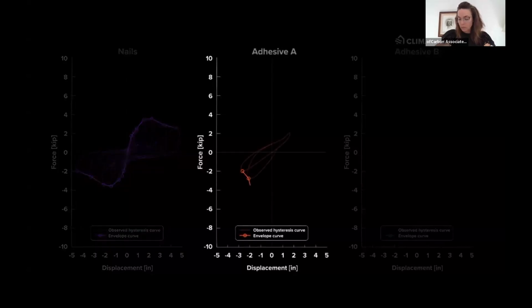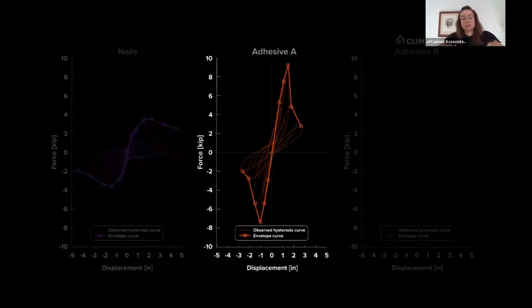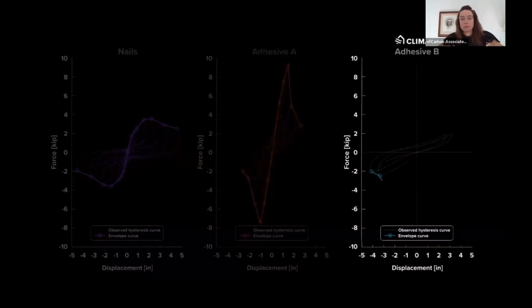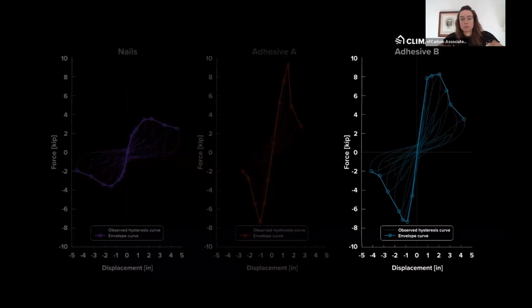The specimen consisting of nails and polyurethane adhesive, labeled Adhesive A, shows better displacement than the nails-only wall, and while it is strong, it is also somewhat rigid and limited in its ability to dissipate force, resulting in relatively brittle failure compared to Adhesive B. The large area within the Adhesive B hysteresis curve, with its many high-volume loops, shows an extraordinary energy-absorbing capacity.